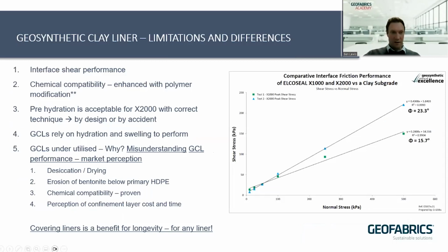And this chart on the right just shows you the impact of an X1000, which is just that woven geotextile on the underside, versus a non-woven or needled fabric for X2000. So X2000 does get about 50% more interface shear performance than the X1000. So if you want to go steeper with your embankments with GCL, then you really should be considering an X2000 or something that has that additional shear resistance.